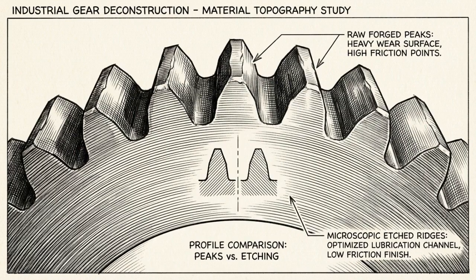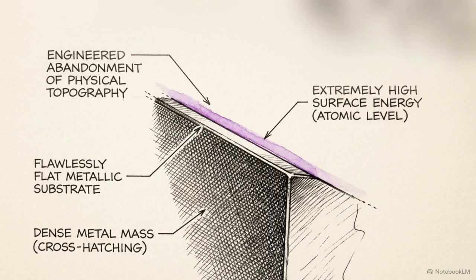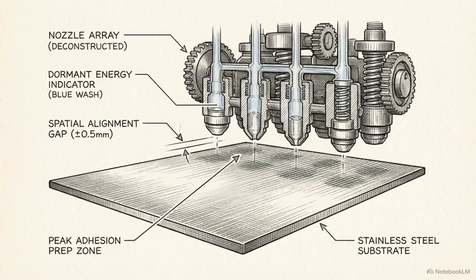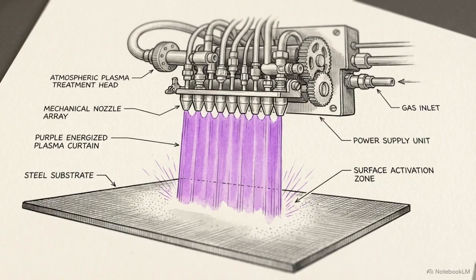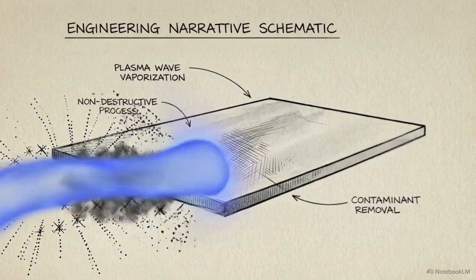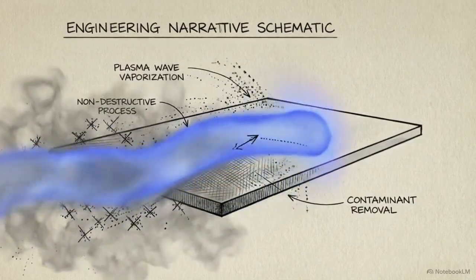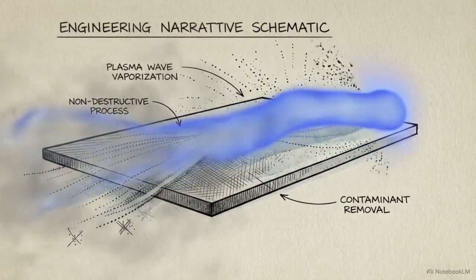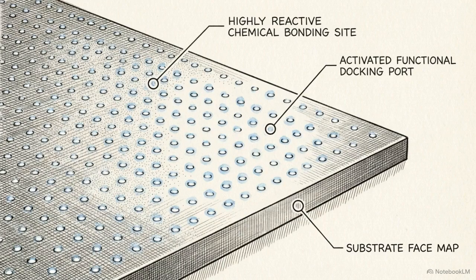Precise chemical etching improves bonding, but it still relies on physical topography. To achieve an absolute mirror finish with maximum adhesion, engineers abandon physical topography entirely and manipulate the metal's surface energy. To get peak adhesion on a physically flawless, smooth surface, the substrate's chemical reactivity must be altered. This is achieved through atmospheric plasma treatment, an advanced surface activation method. Instead of acids or abrasives, a highly energetic wave of plasma sweeps across the metal, non-destructively stripping away residual organic nanocontaminants. More importantly, it activates highly reactive functional sites across the entire face of the substrate.